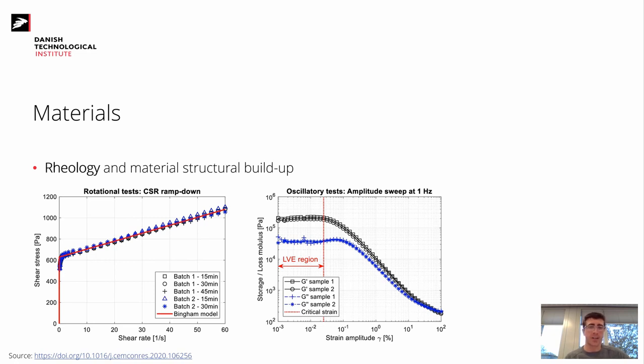The second part is an oscillatory test, a strain scan, to identify at which level of material strains, when you're stacking and squeezing one layer against the other, the material behaves as a linear viscoelastic, or linear elastic, material. So the information from these two tests can be put into an elastoviscoplastic constitutive model.